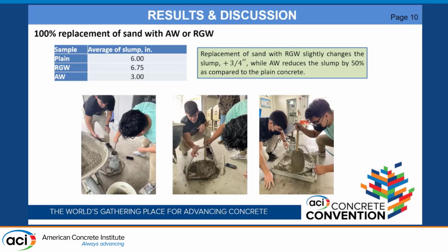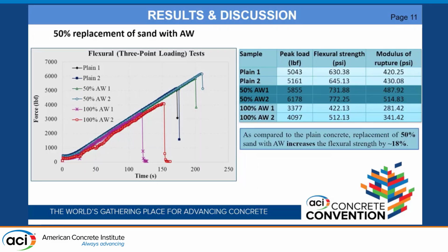And then in terms of workability, we had about a 6-inch slump design. The recycled glass got to about 6.75, so a little bit higher. And then the alumina waste dropped quite a bit, by 3 inches, to 3 inches. So that's a 50% drop. For 100% replacement, we may want to look into some superplasticizers and things like that if you need more workability out of it.